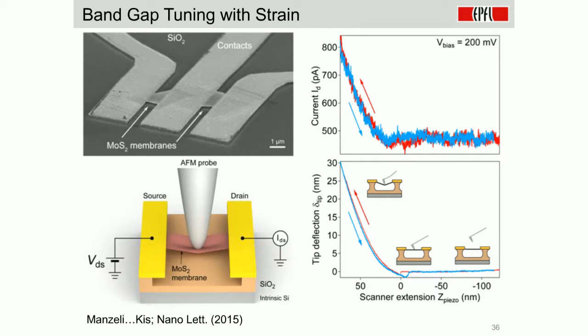of a slightly defective semiconductor, which is what we have in the case of MoS2, and you basically get a conductivity which depends exponentially on the ratio of the band gap to the temperature multiplied by the Boltzmann constant. So basically, by measuring the electrical conductivity and its change with the deformation, we can measure the change of the transport band gap with the deformation of the material.